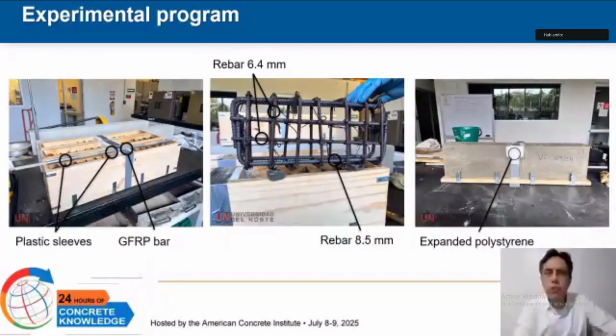These images illustrate important aspects of preparing specimens for bond tests. The first photo shows the wooden molds used to cast the RILEM RC5 beams. The GFRP bars are placed longitudinally with plastic sleeves in the central zone to create unbonded regions and ensure bond activation only within the designated embedment length.